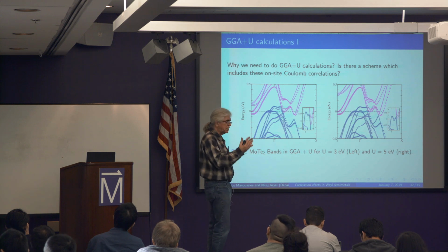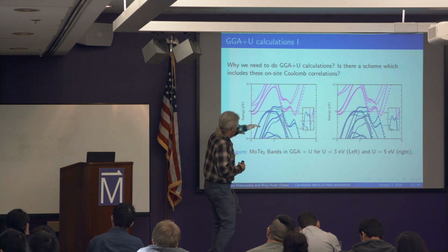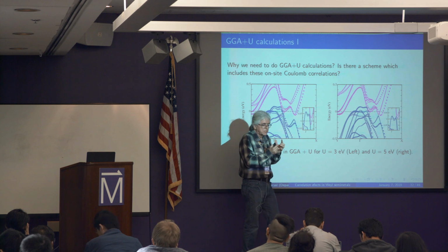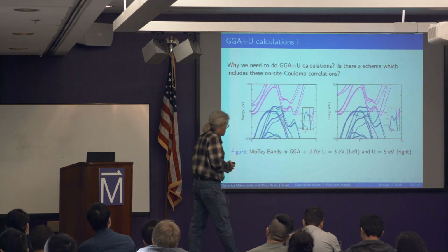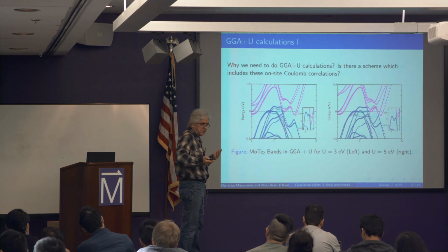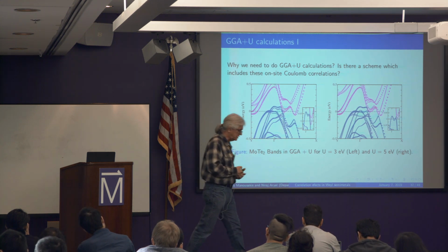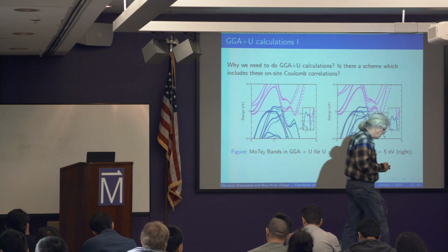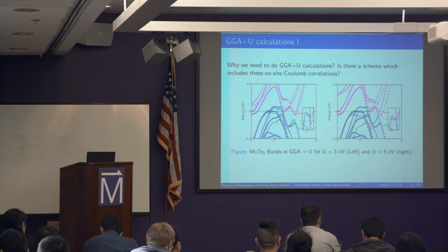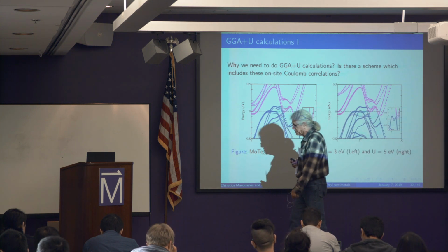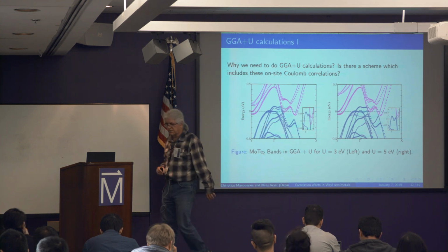And now the holes, because they get filled, the Fermi level goes up, and the hole pockets become smaller, and the frequencies get smaller. This is an immediate effect by just thinking. And so this is exactly what we did in trying to explain the experiment. We moved separately the electron and hole pockets, and many referees said, why are you doing these things? You were supposed to... the only freedom you had when you want to fit quantum oscillation frequencies was just to move the global Fermi level up and down.